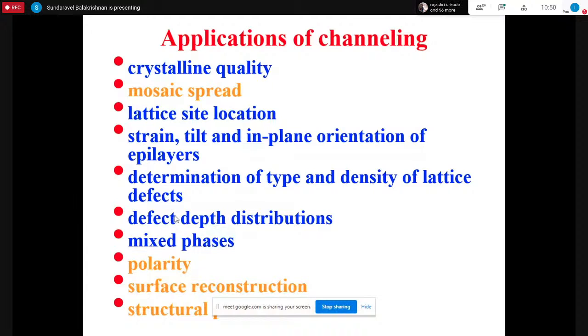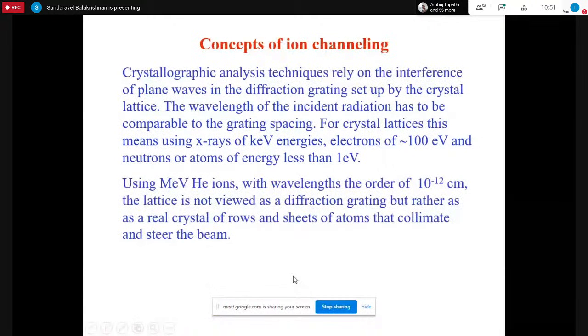And similar to that, using channeling also, we can determine the presence of mixed phases. And polarity, for example, if you take gallium nitride, whether the top layer is terminated with gallium or with nitrogen atoms, we can tell what is the polarity of that substrate. And if you do the experiments under ultra high vacuum, the surface lattice will be getting reconstructed. It won't be of the same lattice like the bulk, and we'll be able to study the surface reconstruction with this technique. And also we can determine structural phase transitions.